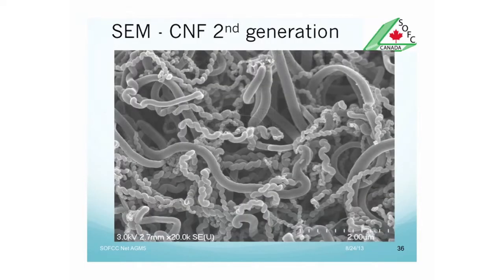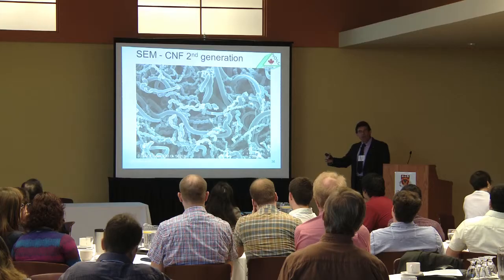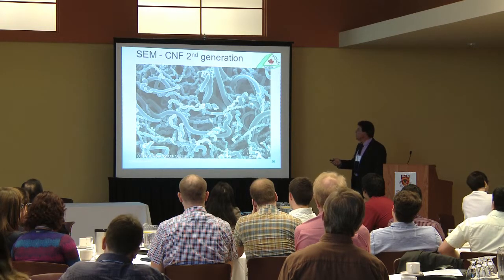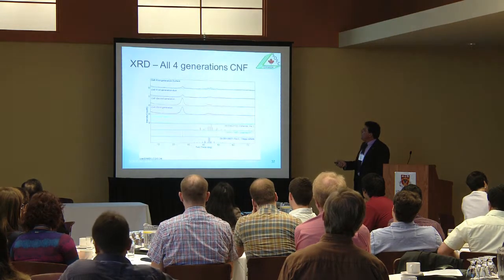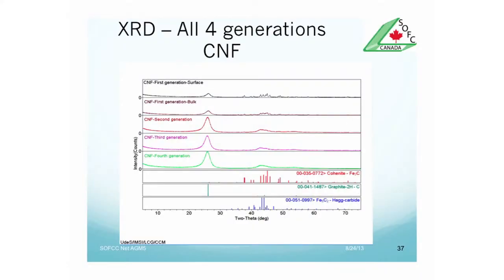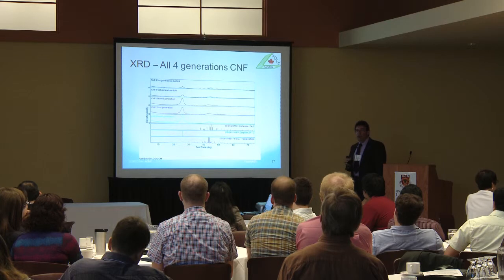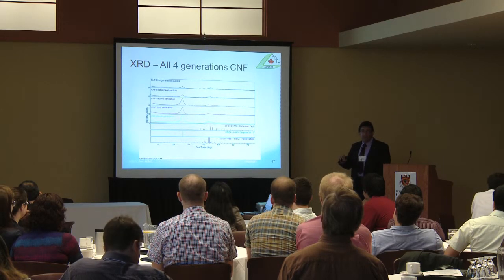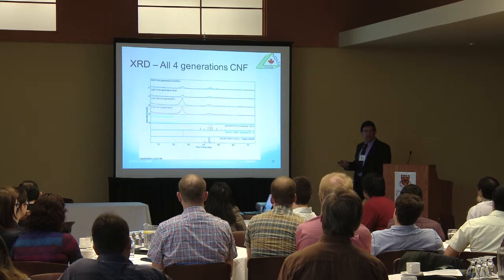These, for example, are additional carbon nanofilaments produced, and we call them second generation because they are the nanofilaments obtained when we are using the nanofilaments as catalysts. And this clearly shows through the XRD that the nanofilaments are acting as catalyst, and as we go to the additional generations, the amount of iron contained in the nanofilament decreases, and logically we have additional carbon obtained for less iron.